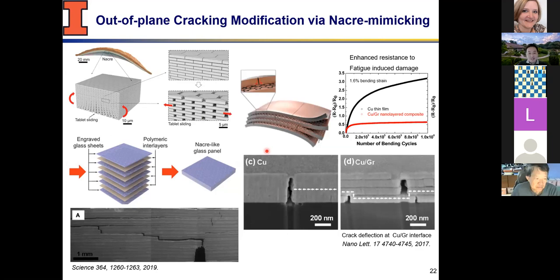If you go to fracture with advanced material, I do need to talk about this. It's not what we worked on, but I just wanted to say that, well, then the question becomes, how do you guide the cracks, so that it's not so straight, for example, if your goal was to increase the toughness of material. And there are lots of bio-inspired approaches where you put hard and soft layers where you create lots of interfaces, where the interface could be a way to guide the cracks across the out-of-plane direction.